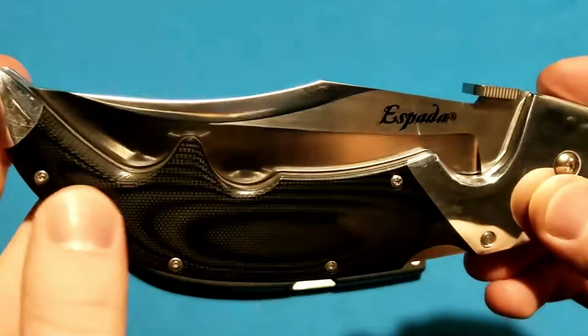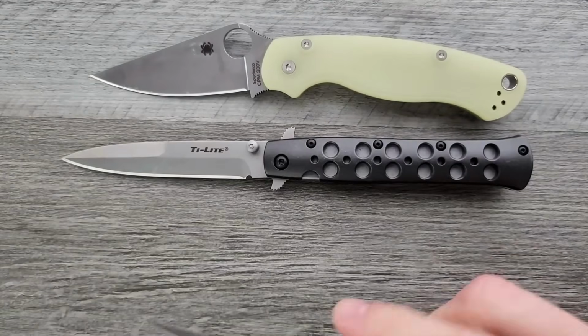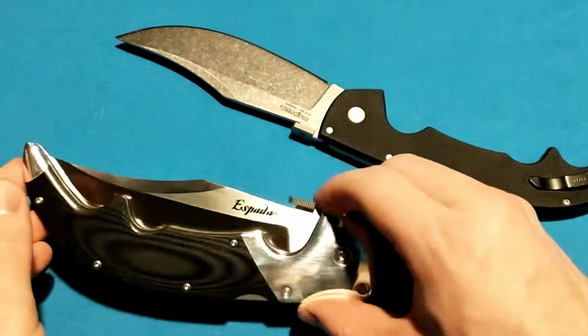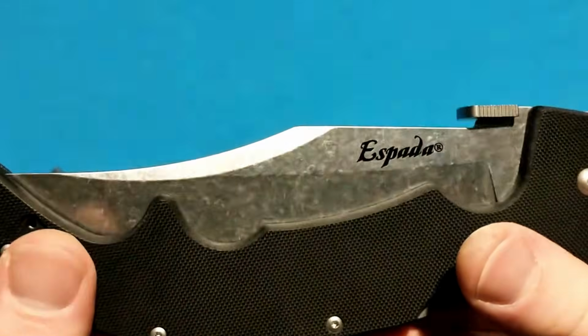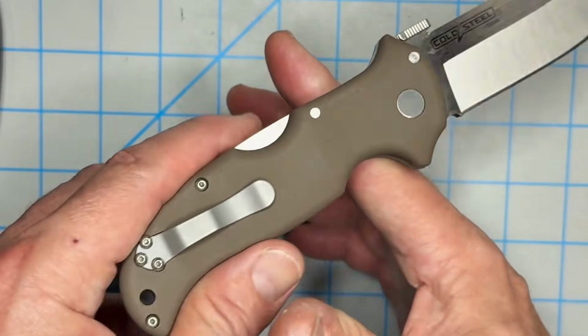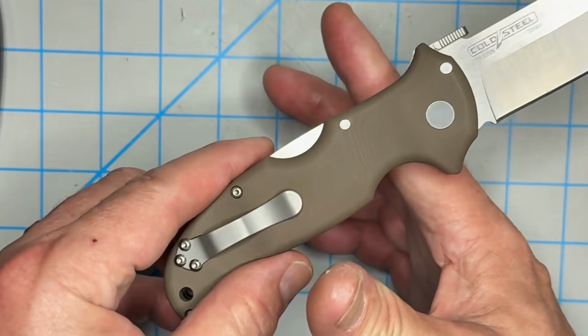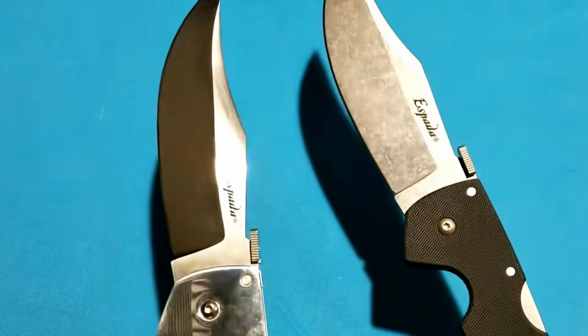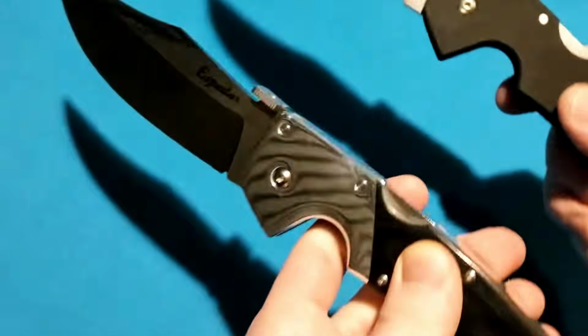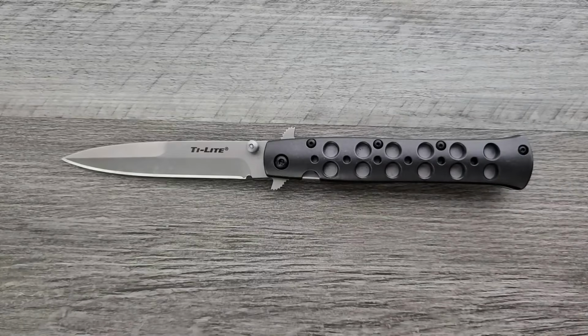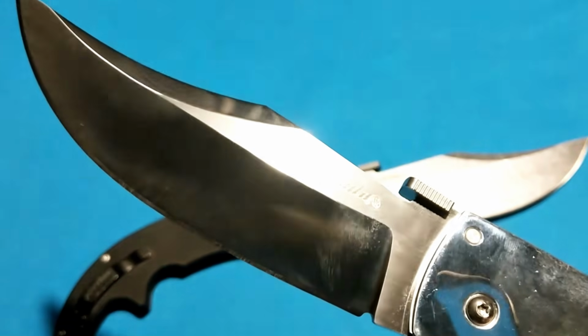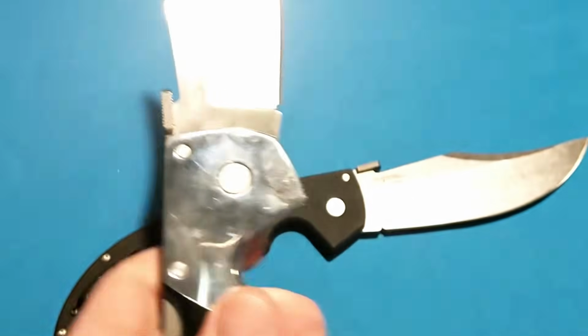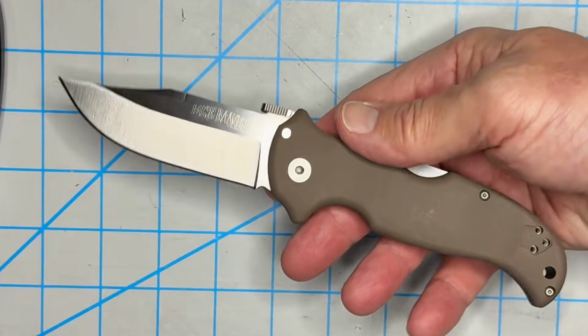The composition is 1.4% carbon, 14% chromium, 3% vanadium, and 2% molybdenum, with a niobium addition that the other two steels on this list do not have. Hardness runs 58 to 61 Rockwell, which is deliberately lower than D2's 60 to 62, because the design goal was toughness alongside hardness, not maximum hardness at the expense of fracture resistance. The 14% chromium is free chromium, not locked in carbides the way D2's chromium is, which means it actually behaves like stainless steel rather than a steel that is marketed as semi-stainless while rusting in the rain.